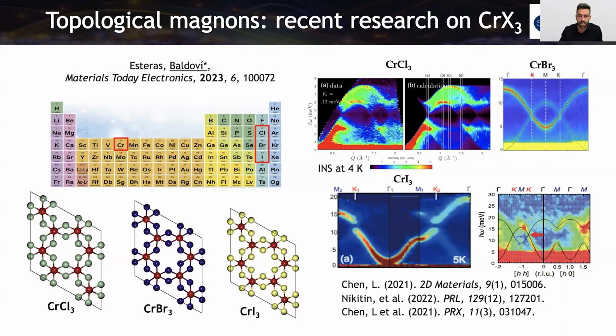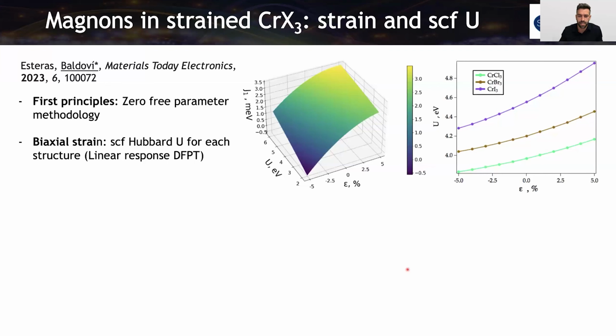In the case of chromium bromide 3, there's discussion in the literature, but it doesn't look like there's an opening of the magnon gap. But in chromium iodide 3, in these measurements at 4 Kelvin by inelastic neutron scattering, we can observe clearly this opening here in the K points of the magnon dispersion. So we wanted to simulate this using a fully first principles approach. In this case, there are 0 parameters in our model.